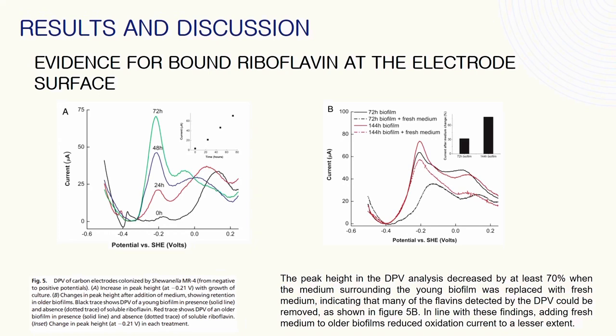The peak height in the differential pulse voltammetry analysis dropped by at least 70% when the young biofilm's 3 days old surrounding medium was replaced with fresh medium, as shown in Figure 5b. This suggests that many of the flavins detected by the differential pulse voltammetry could be eliminated. This result is in line with the notable reduction in oxidation current, 75% in young biofilms, shown in Figure 5a.